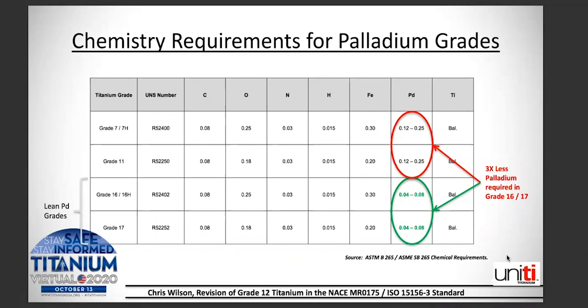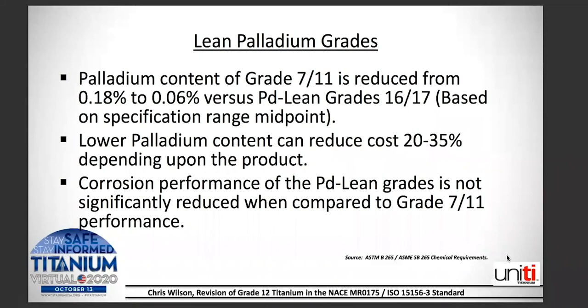Now, why is that? The palladium content of grade 7 is reduced from 0.18 to 0.06 in the lean palladium grades. That's based on the specification range midpoint. The lower palladium content can reduce costs by 20 to 35% depending on the product. Corrosion performance of the lean palladium grades is not significantly reduced when compared to grade 7.